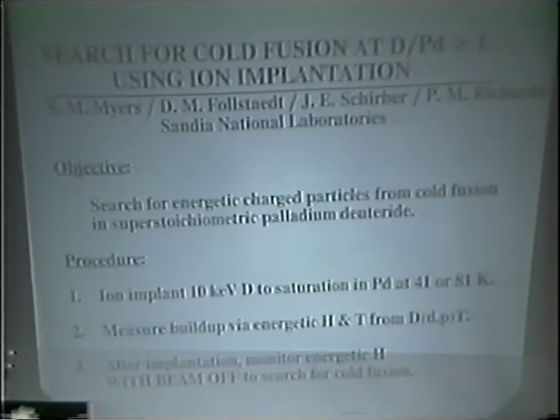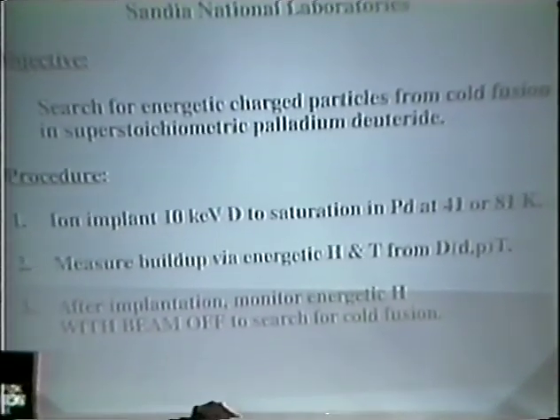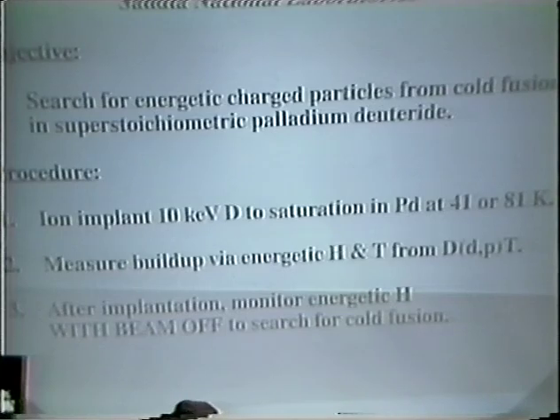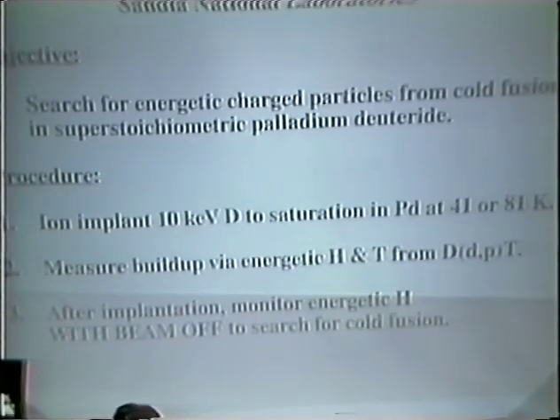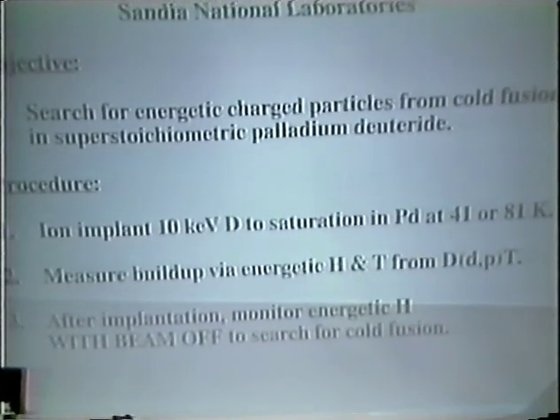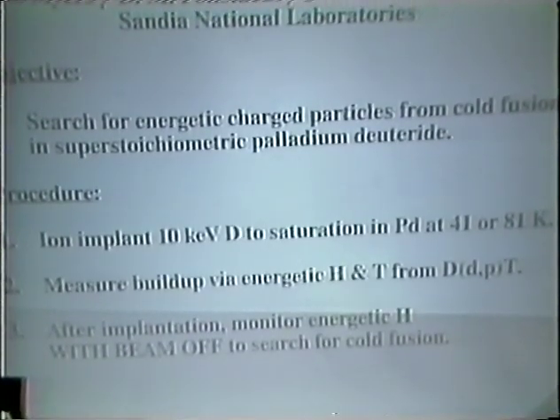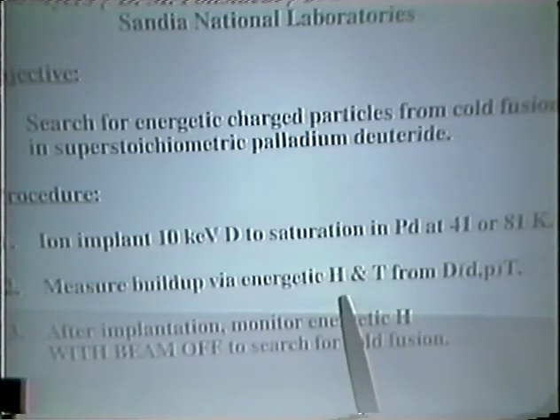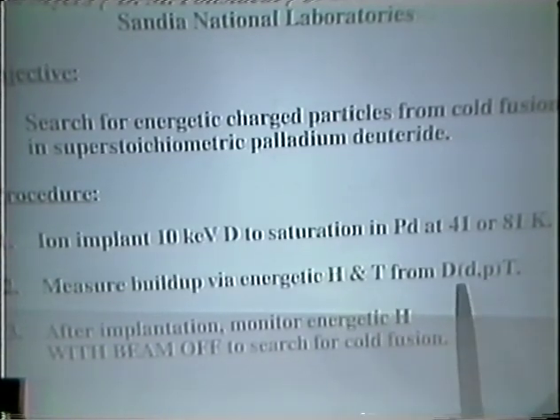Our experiment is outlined here at the bottom. We began by ion implanting 10 kilovolt deuterium from an ion accelerator into palladium, with the specimen being held either at 40 or 80 Kelvin. The implantation was carried to the point of saturation. During the implantation process, we monitored the buildup of deuterium within the metal matrix by using that charged particle detection system to observe both energetic protons and tritons from the